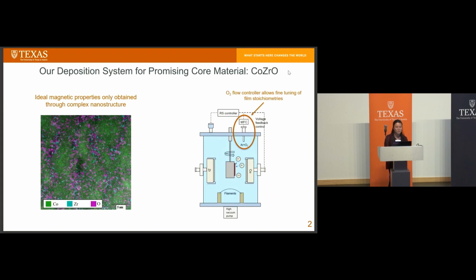So the challenge with on-chip magnetic components today is a trade-off. Generally, core materials that are easier and faster to deposit, like metallic permalloy, typically perform worse in actual inductors. They're usually very lossy. And on the other hand, core materials that have good properties for power conversion typically need to be deposited with processes that are slow and expensive.